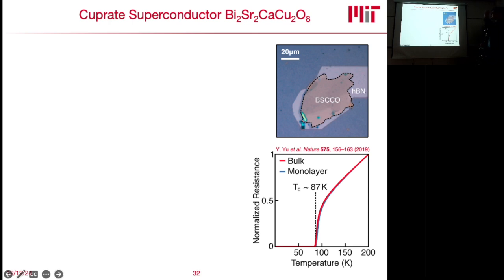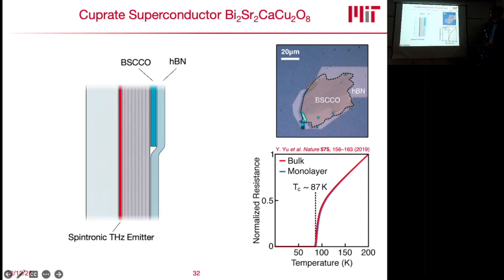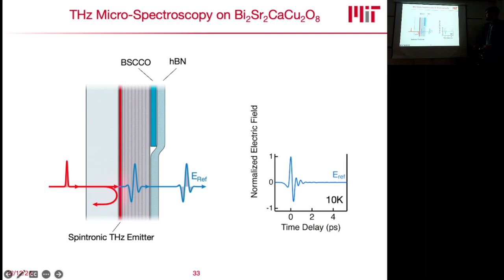And so this is a superconductor with a very high TC. You can see the TC of this material is 87 Kelvin. And so we designed an experiment, as shown here, where part of the sample is not covered, down here, and part of the sample is covered by BSCCO and hBN. What we can now do is a conventional terahertz experiment where we take our reference field by going through just the HBN, because HBN is basically perfectly transparent for terahertz.